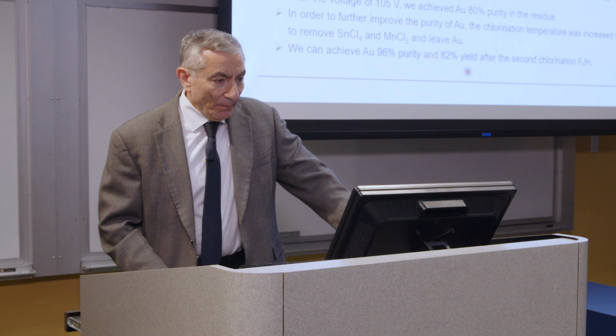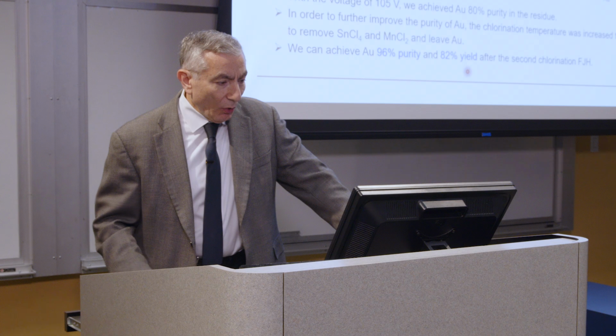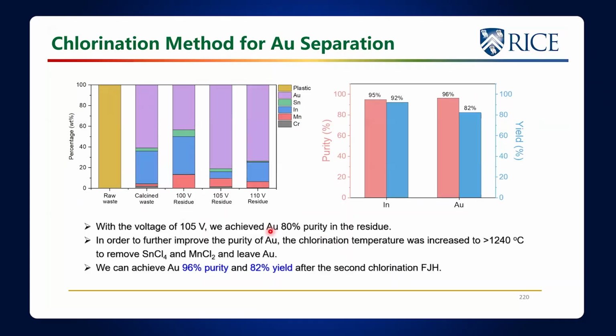Then we want to go after the gold. So at 105 volts, we achieved gold at about 80% purity. In order to further improve the gold, the chlorination temperature was increased to over 1240 to remove the tin chloride and the manganese chloride to leave gold. So for gold, we could get 96% purity, 82% yield after the second chlorination by flash Joule heating.